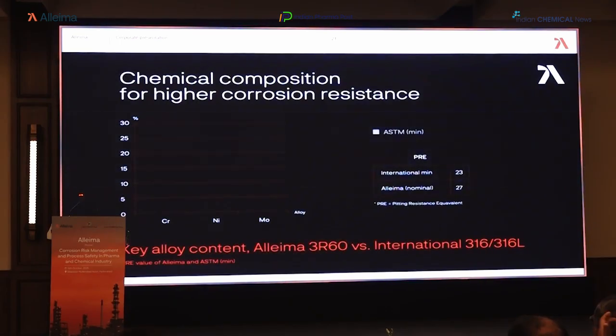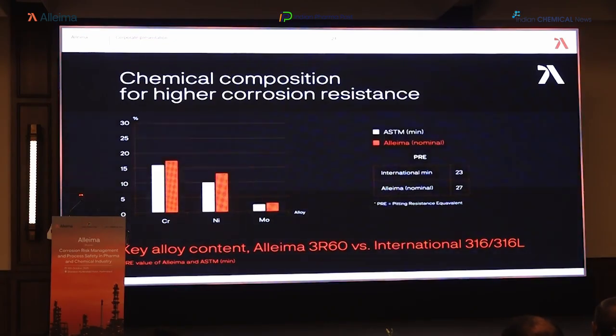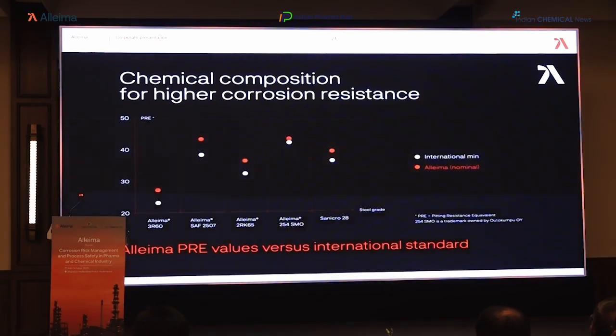Here, you can see how Alleima 3R60 tube, for example, offers superior corrosion resistance compared to the standard 316 or 316L grades, achieving a PRE of 27 versus the international minimum of just 23, thanks to ensuring the optimal chemistry of chrome, nickel, and molybdenum. And here, if we take 5 popular Alleima grades, including SAF 2507 Super Duplex and higher alloy Sanicro 28, you can see how Alleima PRE values exceed the international standard.